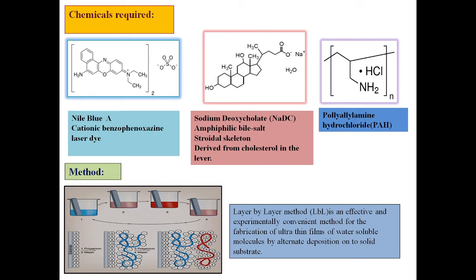Now we want to know how we construct the ultra-thin film. The film was constructed by the LBL self-assembled technique. Layer by layer is an effective and experimentally convenient method for the fabrication of ultra-thin films of water-soluble molecules by alternate deposition onto a solid substrate.